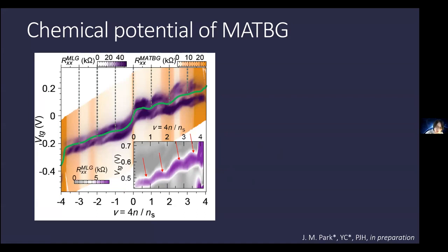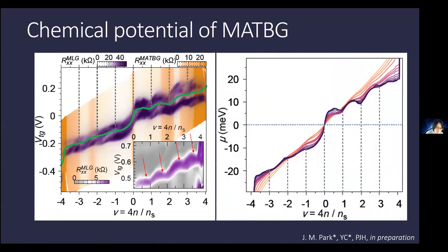So we can do this at arbitrarily high temperatures, as long as the graphene charge neutrality point is still visible in transport. The negative compressibility itself disappears around 20 Kelvin, but the modulation in chemical potential, which signifies the phase transition physics, persists up to 70 Kelvin. So we're trying to obtain now a more quantitative understanding on this, and the result would be posted quite soon.